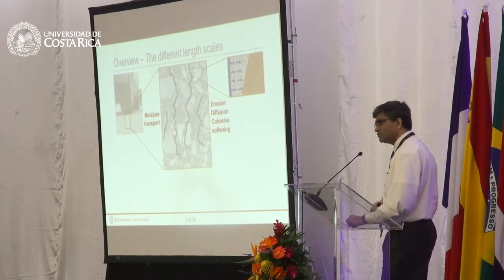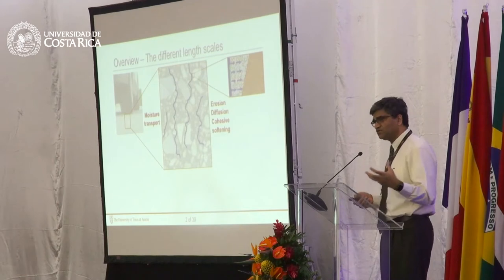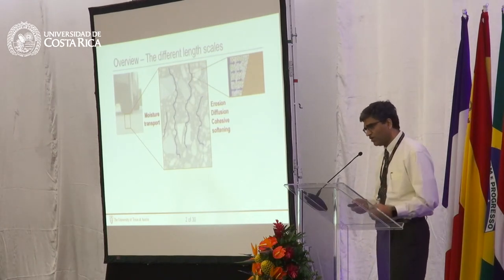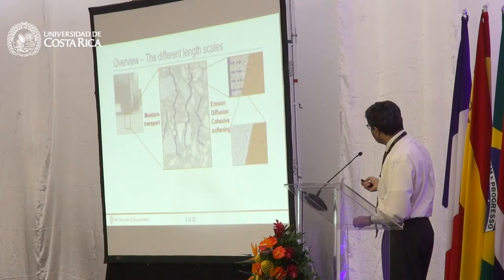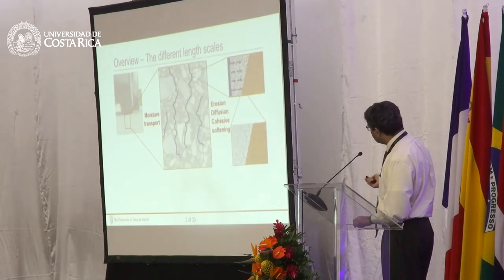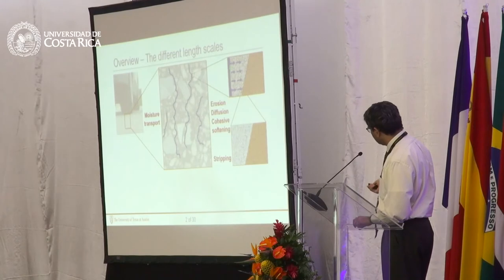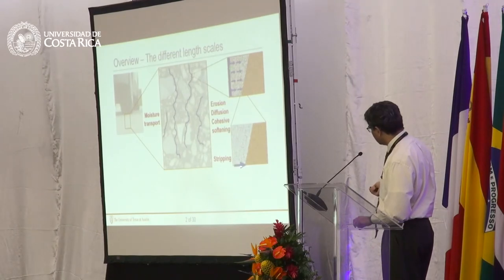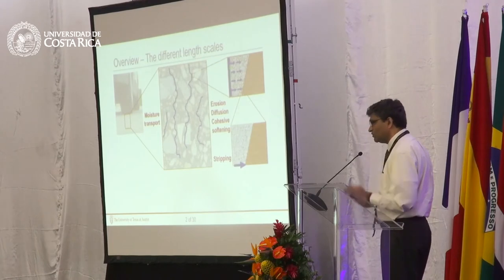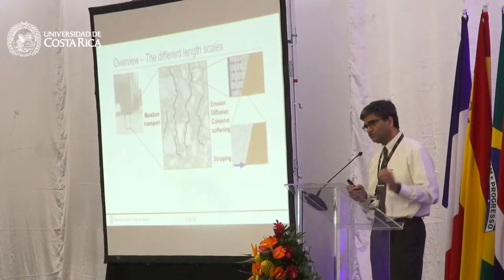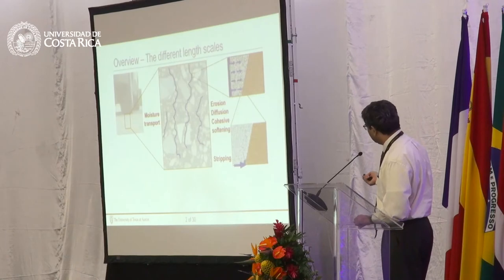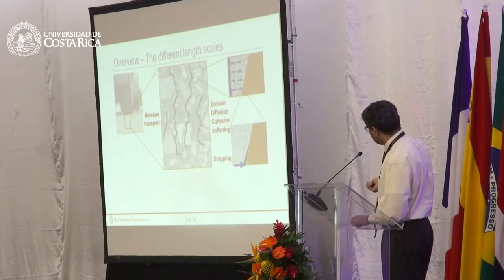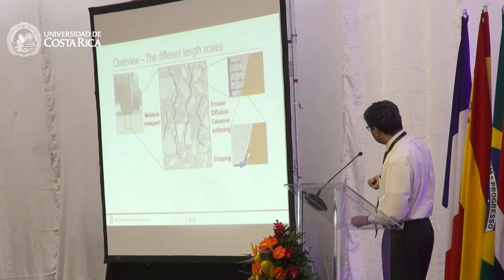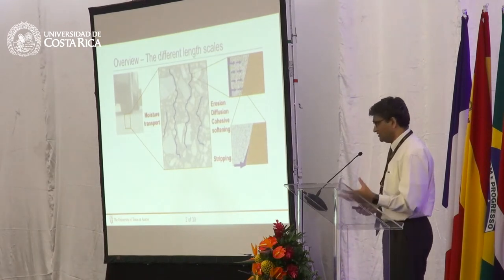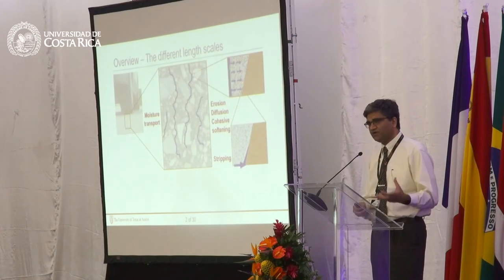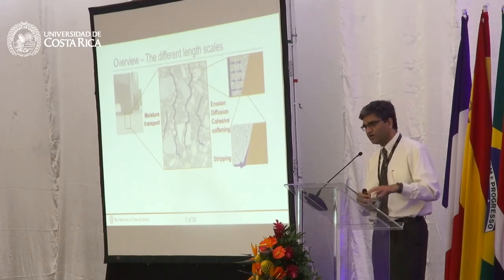As the moisture diffuses, it tends to soften the material, it tends to reduce its mechanical integrity, its mechanical properties, and weaken it. The last step is once the moisture makes its way to the coarse aggregate particle, you see its effect, what we commonly call stripping, where the moisture gradually peels off the asphalt from the aggregate surface. And this is driven by thermodynamics. I'll come to that in a minute. You have water getting in between the interface of the bitumen and the aggregate. Water is a very polar liquid, and thermodynamically, it prefers to get into these interfaces.